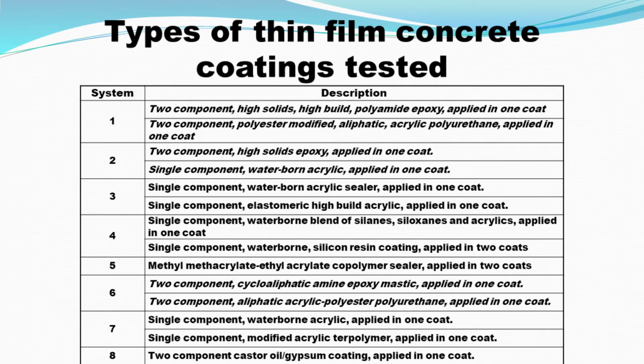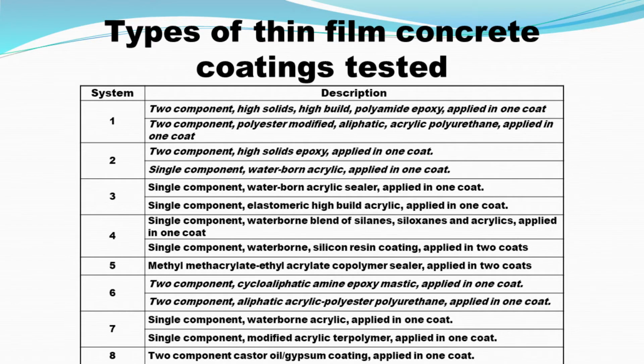Ultimately, 8 systems were submitted and considered for evaluation. Generically, we had a 2-component high solids, high build polyamide epoxy with an acrylic aliphatic polyurethane finish coat. Another was a high solids epoxy with a waterborne acrylic finish coat, then a waterborne acrylic sealer with an elastomeric high build acrylic finish coat. System 4 was ultimately withdrawn because at the time of submission,